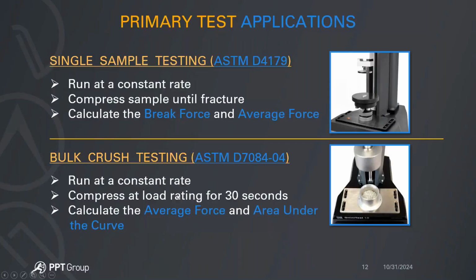Now, the primary test applications are, again, single sample testing that you'll find in ASTM D4179. This is where you're testing just a single pellet. And these are usually compressed until fracture or break, either side loading or top loading, depending on what the particular sample or product requires. Again, most testing applications for single pellet or catalyst testing will involve running the test at a constant rate, compressing until the sample fails or fractures, and then calculating the break force and the average force.